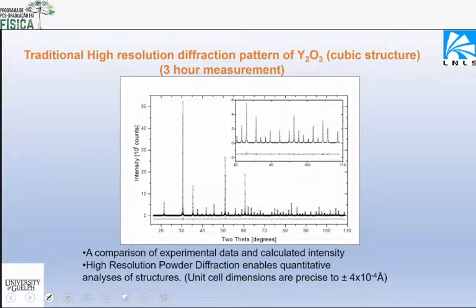So diffraction. Here's the diffraction pattern that I took back at the Brazilian synchrotron, and it's a very nice pattern. So if you think about X-ray diffraction, you think of Bragg's law, right? Lambda is equal to 2d sine theta.